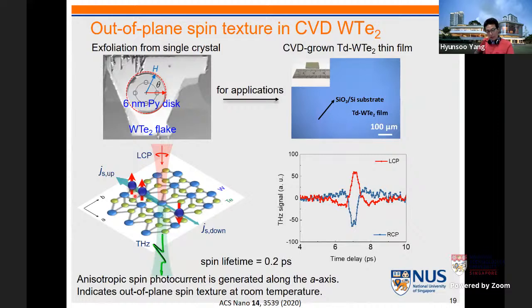Now, if you apply charge current along the a direction, and then from the perspective of electrons, you look at the potential on your left side and right side, you can see atomic arrangements are very different. That indicates the crystal potential is tilted. So that indicates you can also have a tilted spin current generation that will give us an out-of-plane component using the current-induced spin texture.